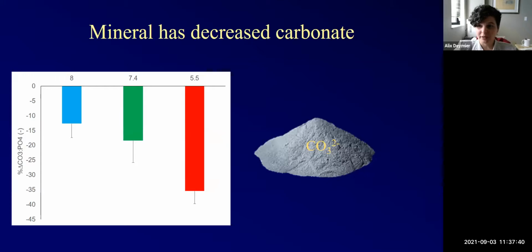Now, if we do Raman, here's the change in carbonate to phosphate. We see that just like in the bone, we have a decrease in carbonate. So the carbonate is lost, and the amount of carbonate that's lost is dependent on the pH. So once again, we seem to be doing all the right things. These crystals are appropriate. They're behaving in the same manner. Good to go.